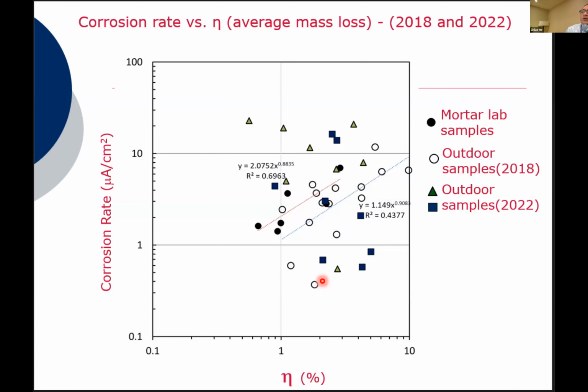in the structure. So here are a couple of additional plots showing the relationship between the eta and the corrosion rate. The green symbols and the blue symbols are for the samples that were obtained as part of this project, and the empty circles are some that were done before. So it is possible that now that these samples are older, some of the corrosion rates are larger and comparable to the mass loss, average mass loss observed.